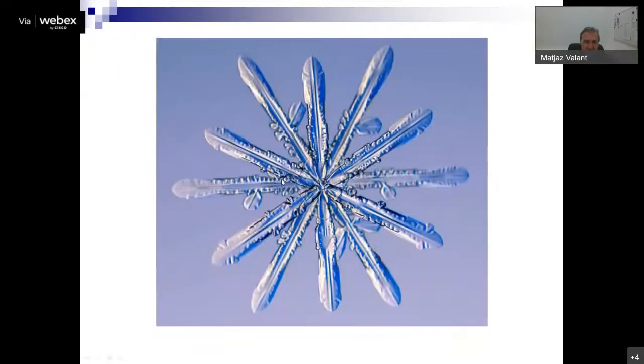And now I think I came to the end of this lecture. And the reason I'm showing you this beautiful snowflake is not that the Olympics finished yesterday, but because snowflakes wouldn't exist if there weren't structural defects in ice. The snowflakes are a result of the structural defects in ice. So what you see here in one branch of the snowflake is a dislocation line. And this is the tip of the dislocation, and the ice grows along the dislocation very fast, but normal to the dislocation very slow. For that reason, we get these branches of the snowflake.